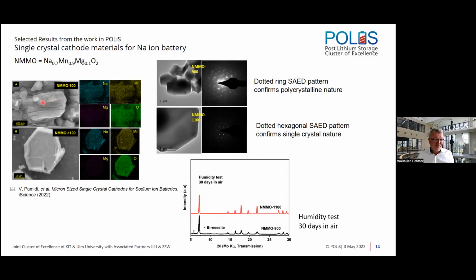So you see here two electron micrographs, with a polycrystalline system that was heated to 900 degrees centigrade, and here a crystal that was heated to 1100 degrees. And then you really get a homogeneous crystal here. You see that also in the SAED pattern, which confirms that you have a single crystal nature. And these materials are pretty stable.